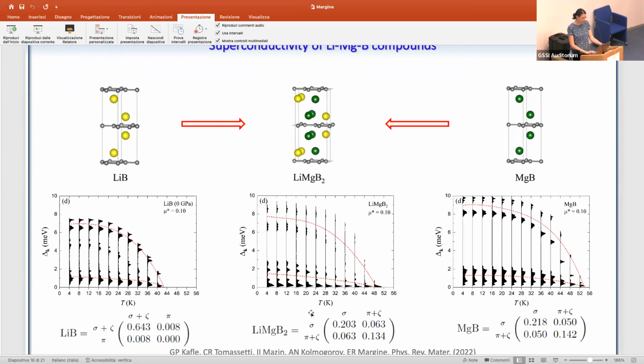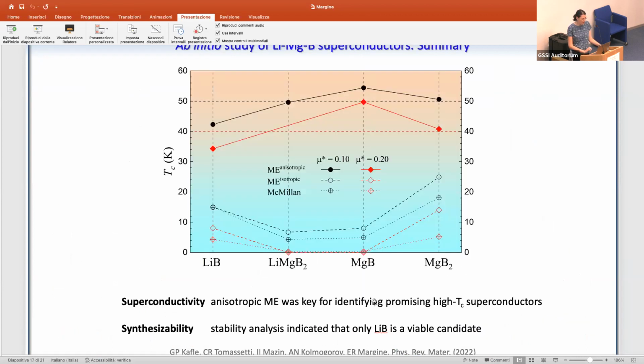And finally, here I am also showing the contribution to lambda coming from the sigma and the pi states. In this case, because of the way the Fermi surface is distributed, the pi and the nearly free electron states are always coupled together, so it's not easy to disentangle them. But what we can see is that while in lithium boron there was zero contribution from the pi states, now, similarly to MgB2, we have significant coupling that can come from the pi states, and slightly larger coupling that comes from the sigma states. So that's a summary of our results.